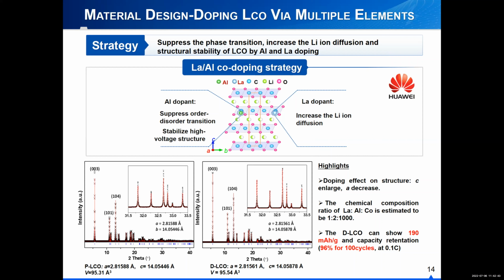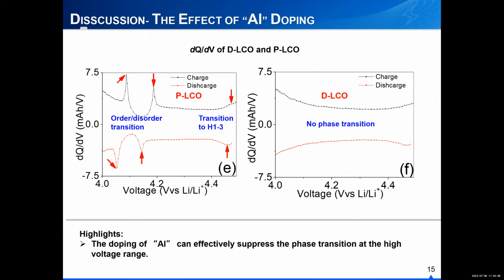That means we can extract about 190 milliampere hour per gram capacity from these materials, and also the stability is very good. Now we get very good data, right? We just try to know why this material's performance is so good. We can also get some information from electrochemical data. So now this is the pristine LCO. Normally, the pristine LCO will experience two phase transitions, the order-disorder transition and the transition to the H1-3 phase. But when the aluminum has been added into the material, the doping of aluminum can effectively suppress the phase transition at a high voltage range. Doping lanthanum can also increase the lithium ion diffusion coefficient, but I didn't mention it right here.